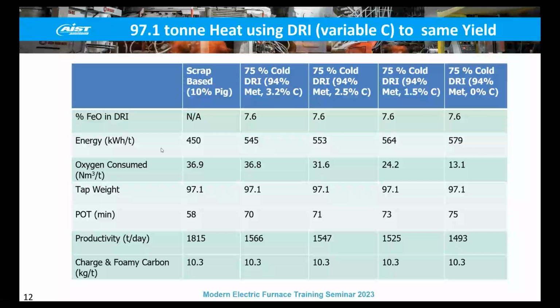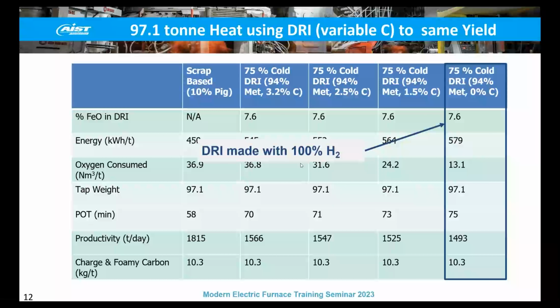Once again, this is that same chart, and he's really trying to point out that DRI made with a gas-based hydrogen process, with kind of a 94% metallization but no carbon, still requires a higher energy input. You're looking at slightly reduced productivity, output of the facility, and longer power-on time. So it's still looking at, say, cold charged.